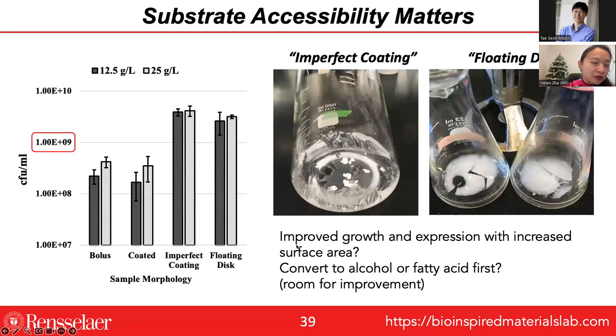And what we were able to see is, first of all, we did get good cell growth. And the manner in which we give it to our cells matters. Whether you create a bolus, like a piece of it in the flask, or you spread it out as a disc and then you rough it up a bit, seemed to make a difference. At the end, what we got was a disc of this waxy material, which is not soluble in water, by the way. It's one of the challenges. It just floats around and will break up a bit in the shake flask as we're culturing. And of course, there's room for improvement even on this front.